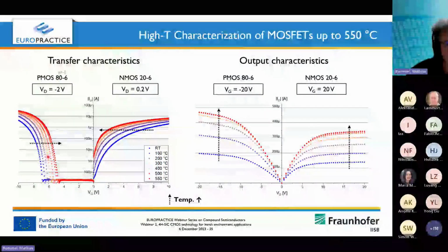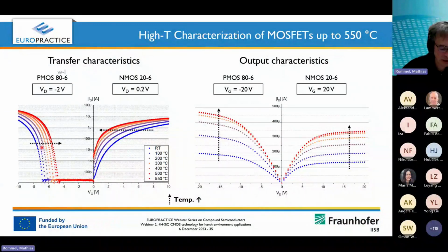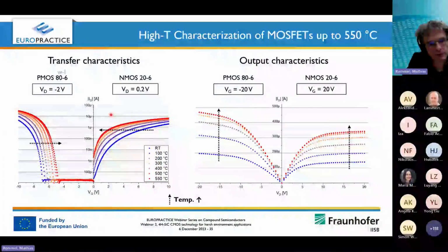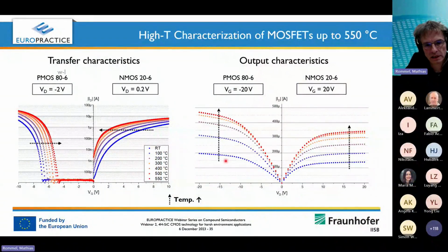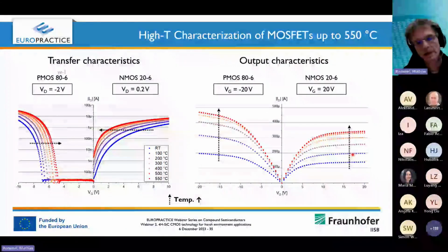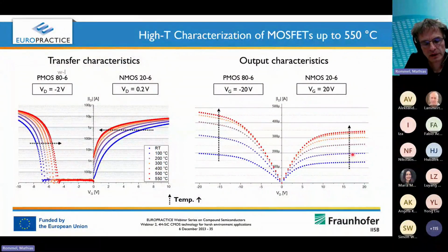So what you can see, and what we also saw from the slide I showed before with the threshold voltage dependence on temperature, is that with increasing temperature you basically get smaller threshold voltages and overall higher currents, which you can also see here in the output characteristics. And that's something we see both for PMOS and NMOS. So that's also something which is not the same as for silicon, because we have different mobility effects or models which dominate the carrier transport here.